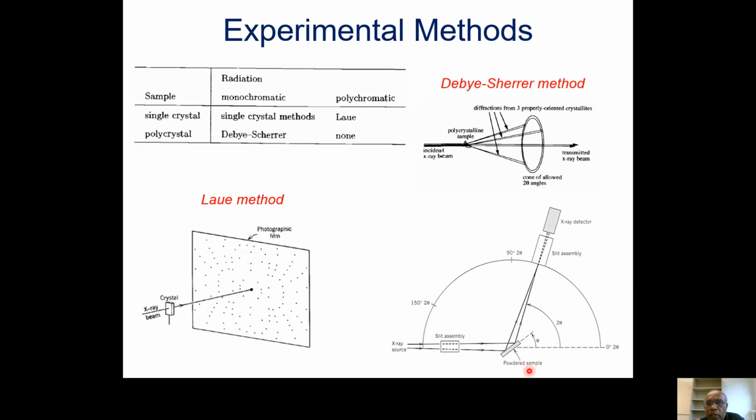This last figure shows you standard X-ray setups. This is for the Debye method. You have the sample here, and the monochromatic light coming in from the source. They detect around this goniometer, so we call this a 2θ technique. Depending on that, you can get the information. Basically, you have fixed your source, then you move your detector around this goniometer circle.